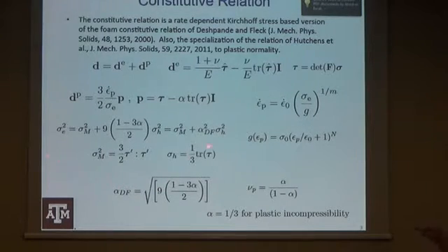The main point is there's one additional parameter, the plastic compressibility. This is the DF, the Deshpande-Fleck parameter. That's their parameter. There's also an effective Poisson's ratio. So either alpha DF or nu plastic characterizes the compressibility. It's a very simple relationship: power law rate hardening, power law hardening. If alpha is 1/3, this is a half, that's incompressibility. When alpha is 1/3, this is, let's see, the square root of 3 times alpha is 1/3, this is 0. So these are different ranges of parameters.